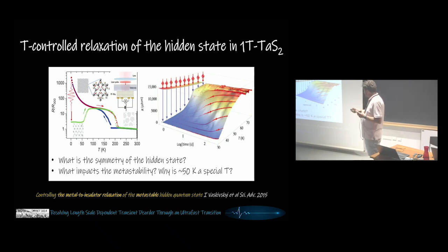So there was this switching that was reported in this system at low temperature, and as you do your pump pulse, you actually make the system more metallic, and this state is long-lived. It actually can live for weeks, according to Dragan. However, you can actually destroy that state, that hidden state, which is not observed in equilibrium, by heating up above